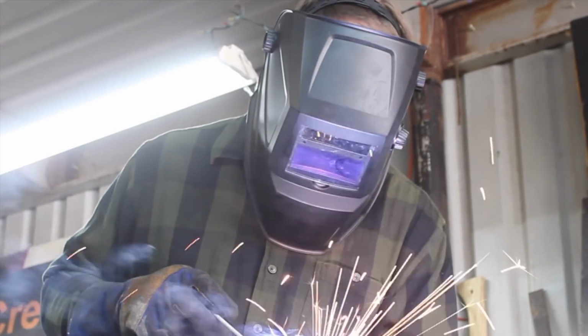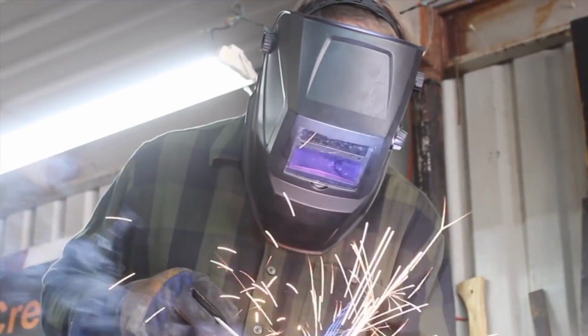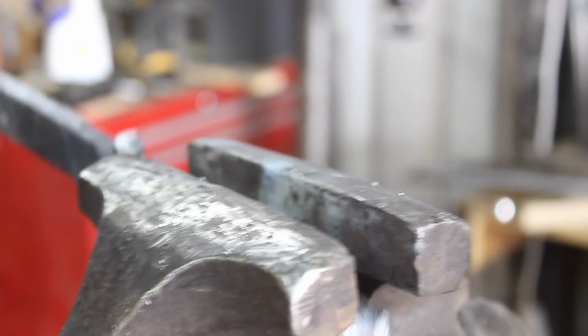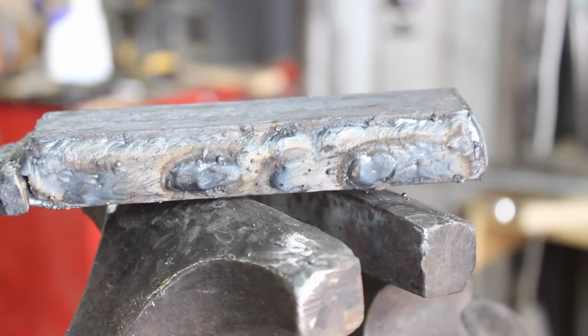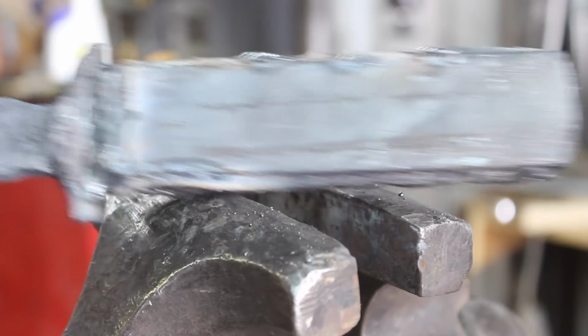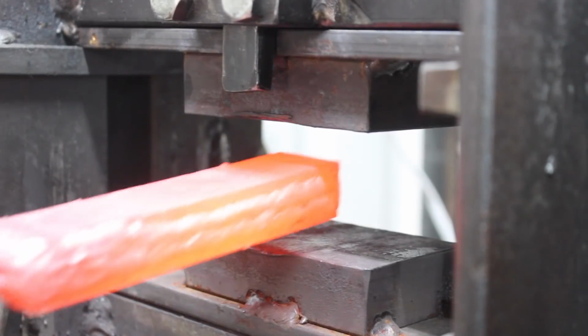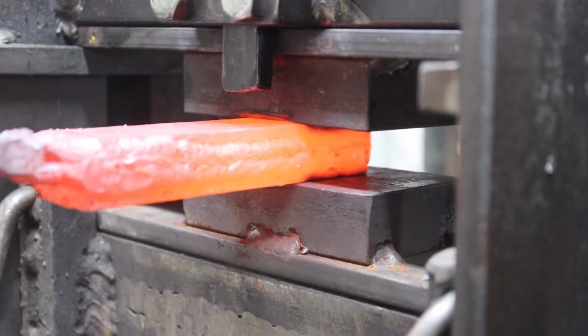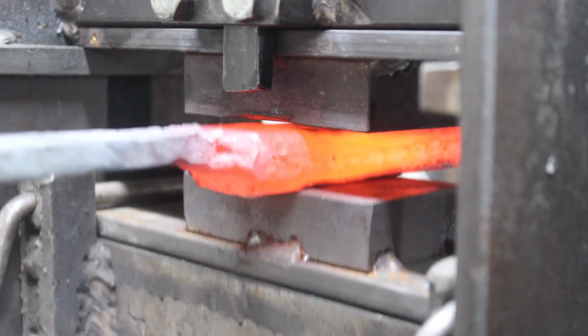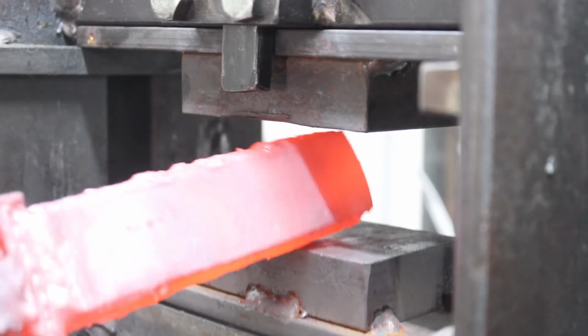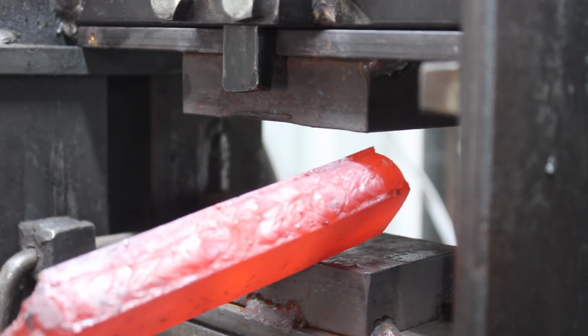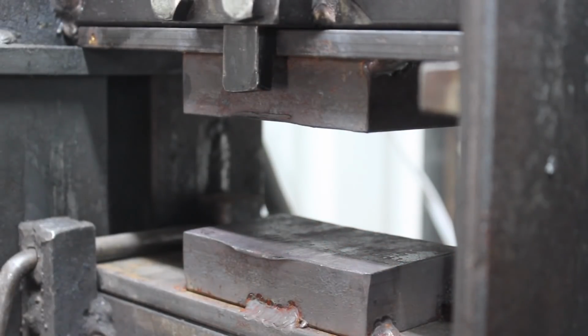So the melting point of copper is about 1984 degrees if I remember correctly, and you want to have everything sealed up. But I was a little worried about melting the copper. I know this billet wasn't completely sealed, so I started forging it at 1600 to 1800 degrees, which in theory should be enough to bond the copper to the steel and accomplish what we're trying to do here.